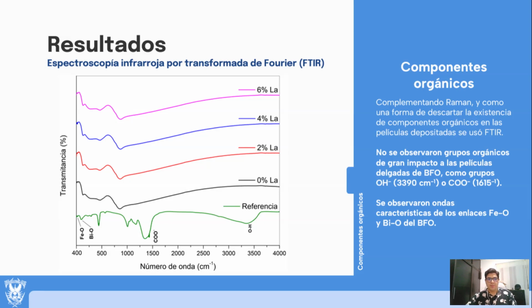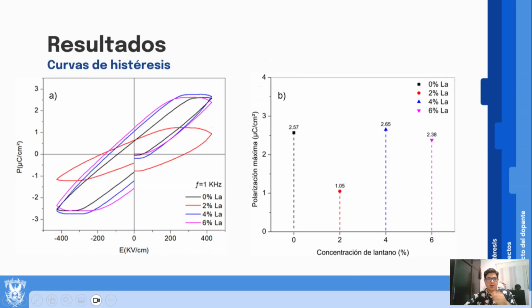This work explored strategies to enhance the ferroelectric behavior of BFO thin films through doping. Electrical measurements using graphite contacts revealed characteristic ferroelectric hysteresis loops, confirming the material's functional properties. While most doped films exhibited promising ferroelectric performance, the 2% doped sample showed significantly degraded behavior compared to others. The results demonstrated that low doping concentrations can negatively impact ferroelectricity, whereas higher doping levels maintained or slightly improved the response. These findings provide crucial insights into how dopant concentration influences BFO's ferroelectric performance for potential device applications.